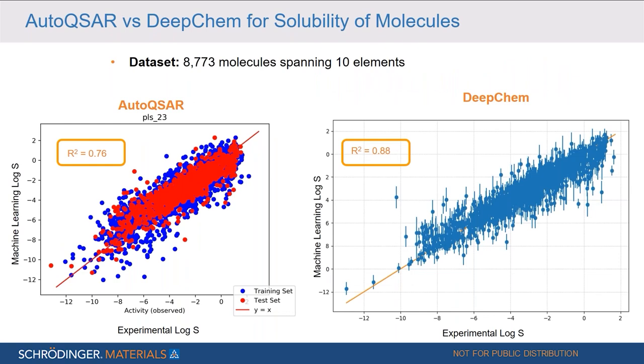There's another example for the prediction of the solubility of molecules, one with auto-QSAR and one with DeepChem. In both graphs, the x-axis corresponds to the experimental log solubility and it spans over a very wide range. We see already with auto-QSAR, we get quite reasonable results. So we get an R-square value of 0.76. But we increase significantly if we use DeepChem, where we get an R-square value of 0.88. So we see that it outperforms auto-QSAR on such large data sets.